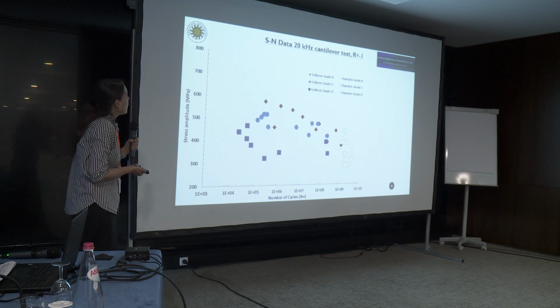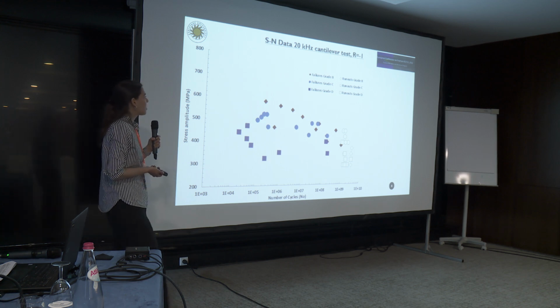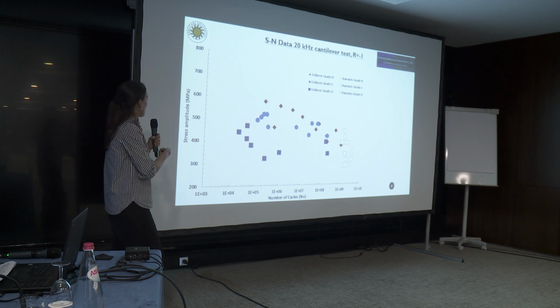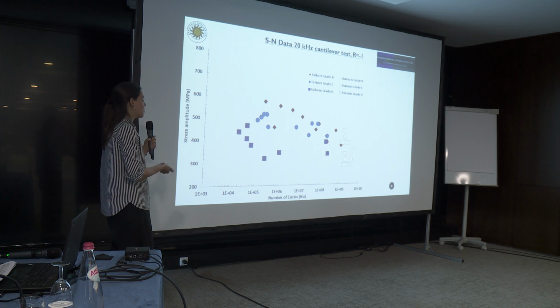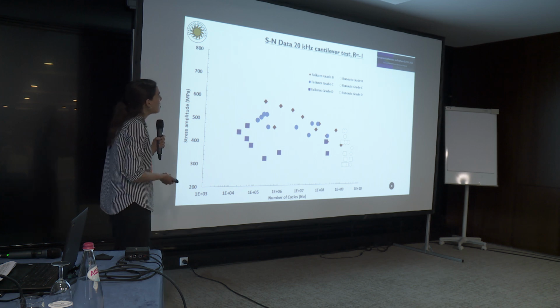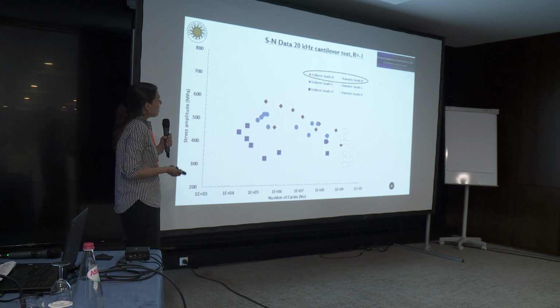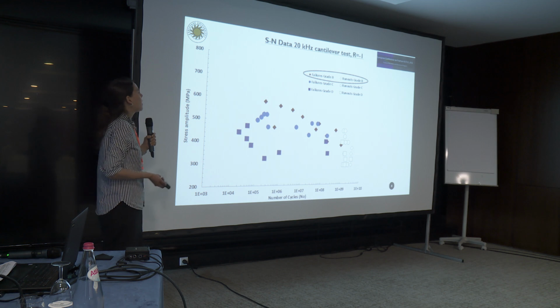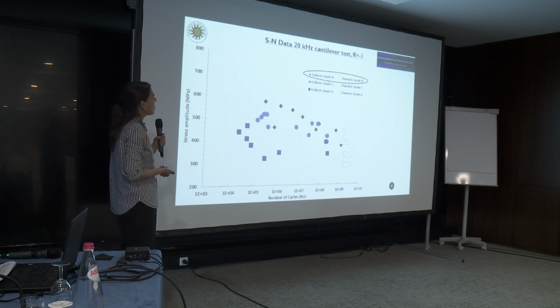Indeed, here is the SN curve for the three different grades. On the y-axis, we have different stress levels, and on the x-axis, we have the logarithmic scale of number of cycles. Grade B has the best overall fatigue strength among the three grades, followed by C and then by D.